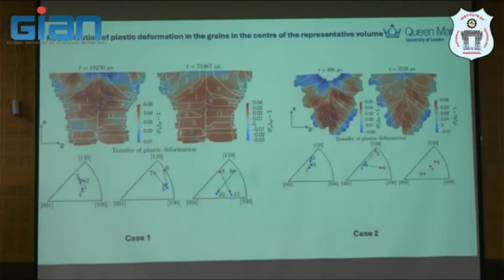If you remember my slide on the high resolution EBSD, you see the soft and the hard grain, which is actually seen here as well. Some grains are not actually single, for example, this grain. So you have different stress levels, and type 2, type 3 actually kick in. You can draw a profile inside the grain, and this is quite impressive.